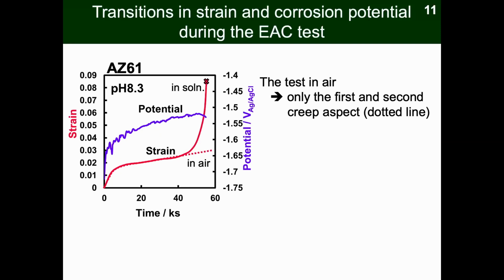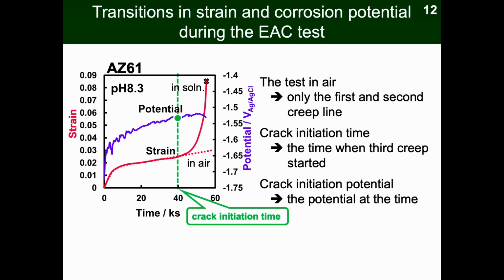So this again shows you the transition of the strain and the strain potential change with time. If you conducted this test in air, only the first and the second creep stage was seen. So we can determine the crack initiation time as the time when the third creep starts. And crack initiation potential here is determined as the potential at this time.